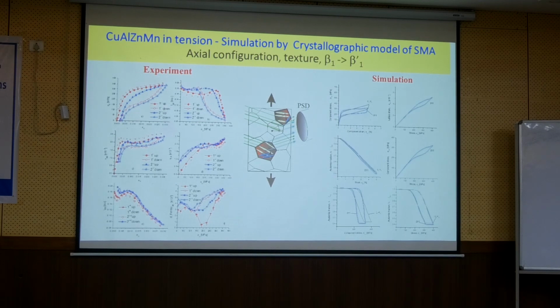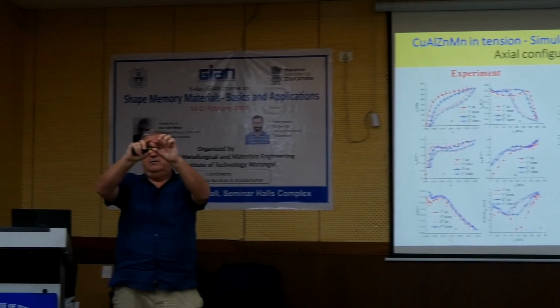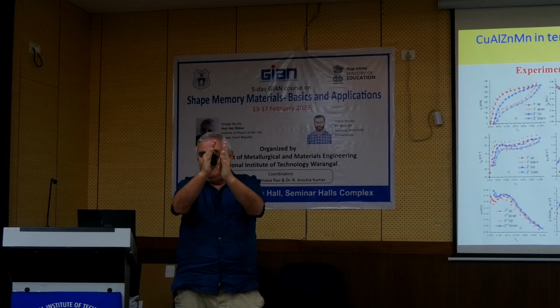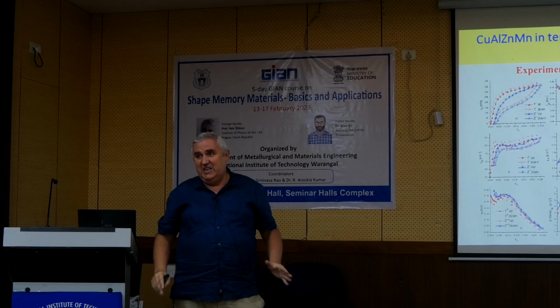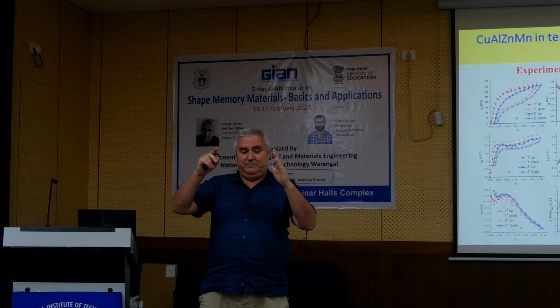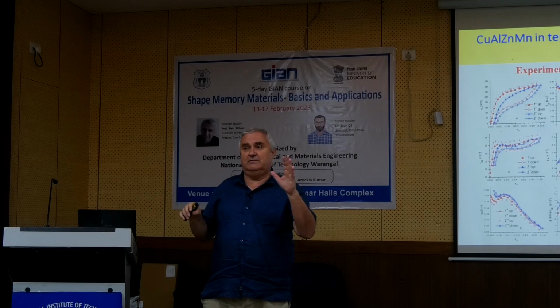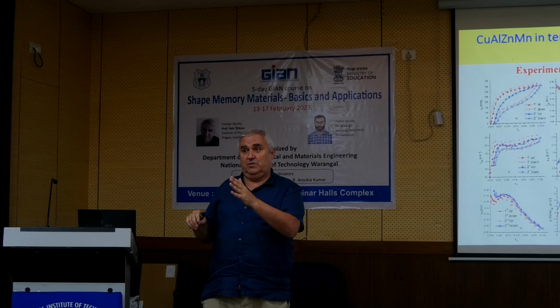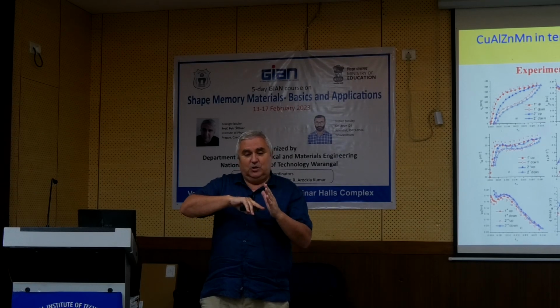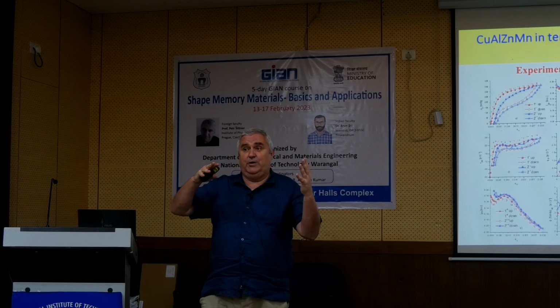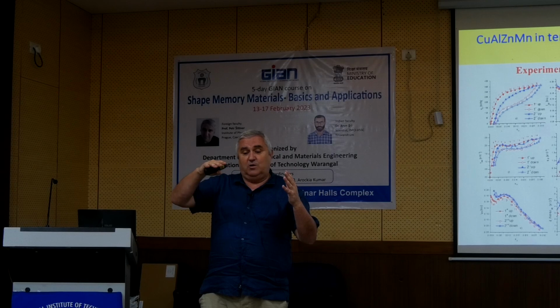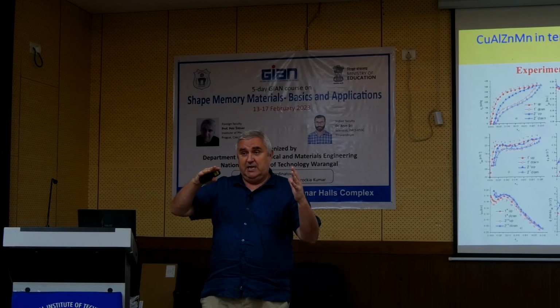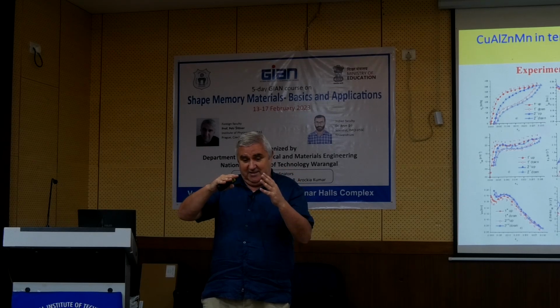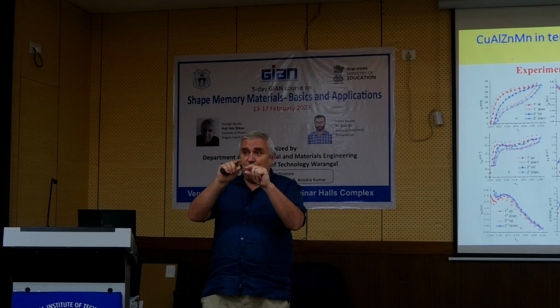And this little plasticity, you can imagine, you have 2 grains, and one will deform plastically. After unloading, this is longer, this is shorter, and what do you remain? It goes back, but at the boundary there is internal stress. So after hundreds of cycles, it kind of stabilizes itself. We did experiments particularly designed for that on nitinol. In the first 2 or 3 cycles, the phenomenon is maximum. But after that, in tens or 100 cycles, it's less and less, so it somehow stabilizes. But what happens is that in every grain, you have some plastic strain mismatch, which introduces some internal stress.